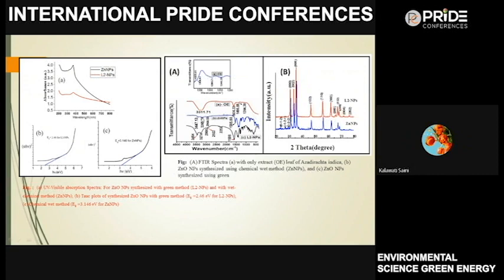These are the FTIR spectra. The red one is regarding only the extract of Azadirachta indica leaves. The blue one is the FTIR for zinc oxide nanoparticle synthesized by the chemical wet method, and the third one is regarding the L2 nanoparticle, which is synthesized using 2 ml of leaf extract.